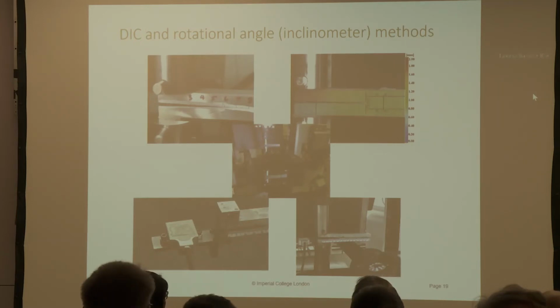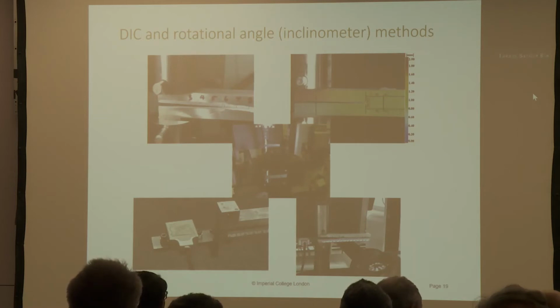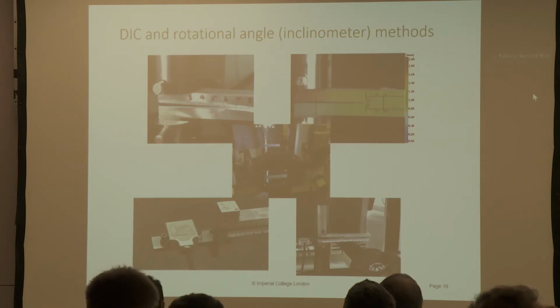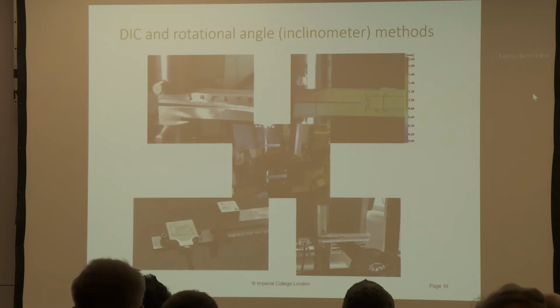And one of the advantages of this technique, of course, is that it can be automated. Particularly thinking of mode 2, where it is very difficult to measure crack length, but often in mode 1 we have significant issues measuring crack lengths as well. So techniques which have the potential to automate crack length measurement are very desirable. Another thing that can be done, so several groups have used these sort of techniques where you don't measure displacements and rotations directly on the surface by DIC, but you use, for example, an inclinometer device. So in the image on the bottom left, you can see an inclinometer is attached to the lower arm of a DCB specimen here, with the idea to measure the rotations.